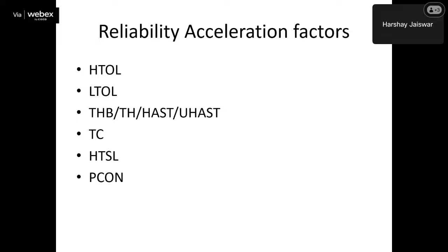It's called preconditioning. With this preconditioning, we simulate the solderability of the product. Preconditioning contains three stages: temperature cycling, moisture soak, and bake. But it's not for 1000 hours. We do 5 cycles of temperature cycling, -40 to 160, five times, then finish. Then moisture soak, which again comes from the qualification plan. We have three categories of moisture soak: MSL1, MSL2, MSL3. For MSL1, we apply moisture soak at 85 degrees and 85% relative humidity. MSL2, 85 degrees and 60% relative humidity. And MSL3, 30 degrees, 60% relative humidity.